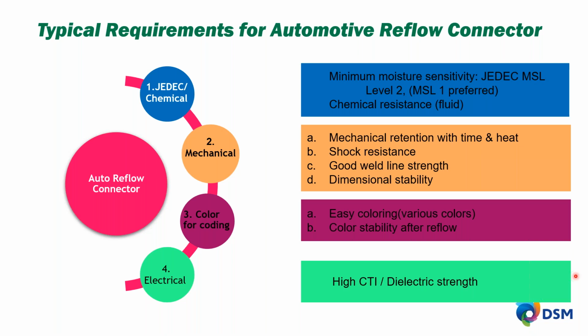It's also a bit of a thermal shock to the material. As the material rapidly heats and then cools through the reflow process, the material is expanding and contracting. And that can cause cracks or defects to appear if the material is not robust enough to withstand that thermal shock process. The material has to have good weld line performance, which is where the melt in the injection molding process knits back together as it flows around open holes or cores. And that weld line strength has to be maintained as well, so you don't start to have cracks or divisions at that weld line area.